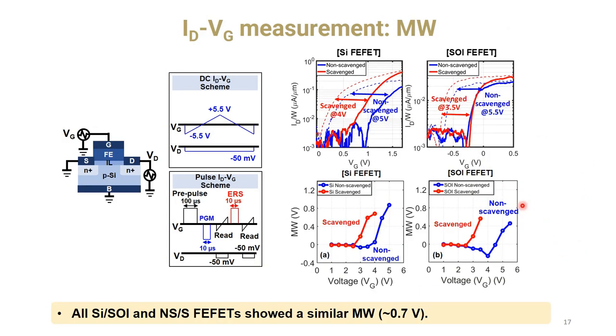And then we measured the memory window. To get the memory window measurement, we measured the IDVG using the DC scheme and also the pulse IDVG scheme. And you can see, depending on the polarization, we had a low VT state and a high VT state, so we can measure the memory window for both the scavenged device and the non-scavenged device. Also, the same thing happens in SOI. For the scavenged device we can measure the memory window, and for the non-scavenged device we can also measure the memory window.